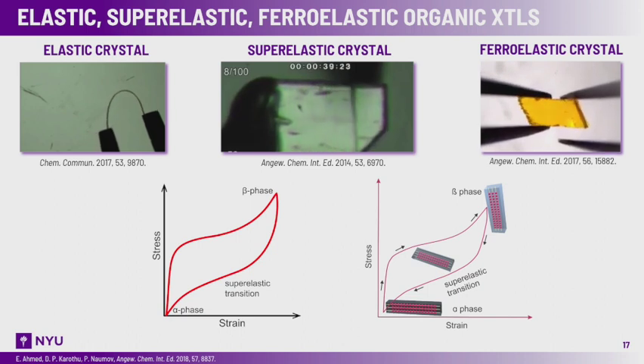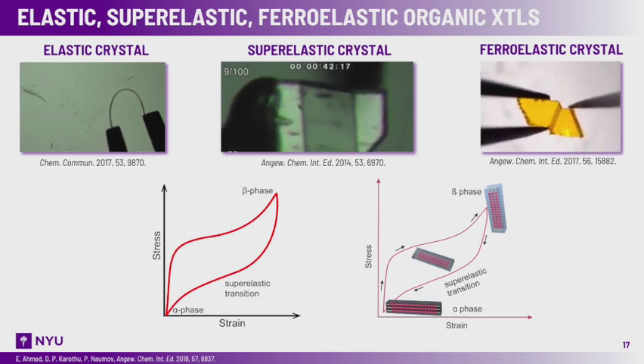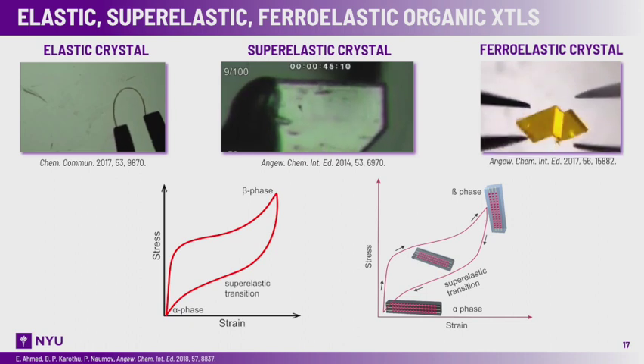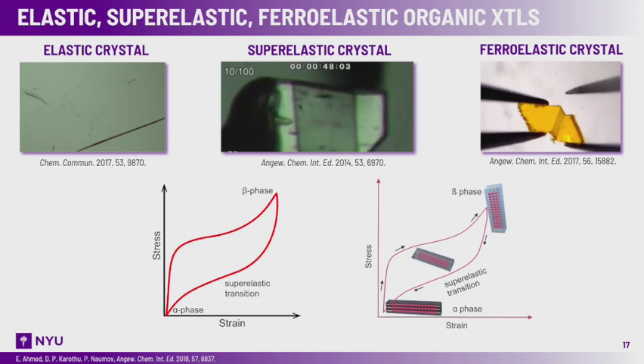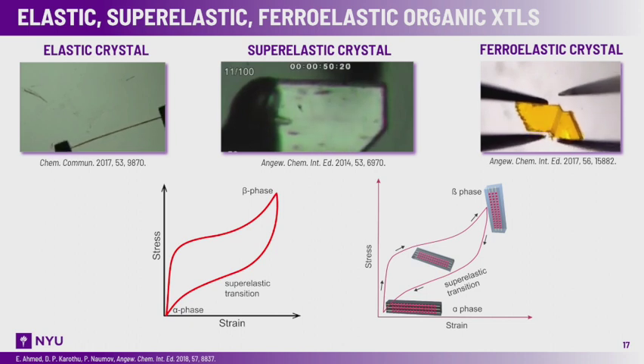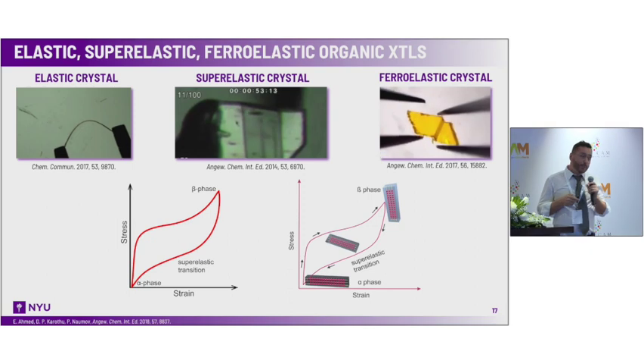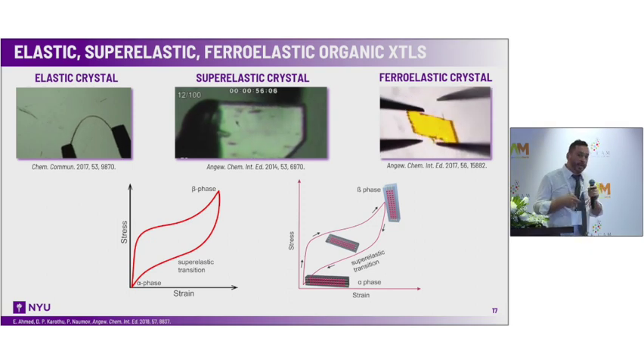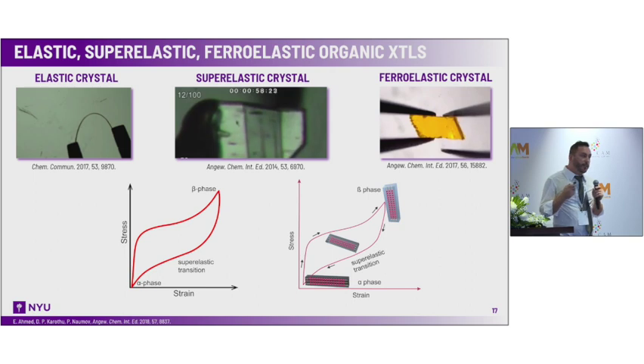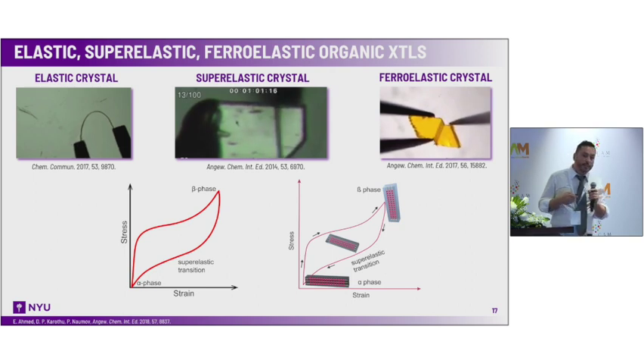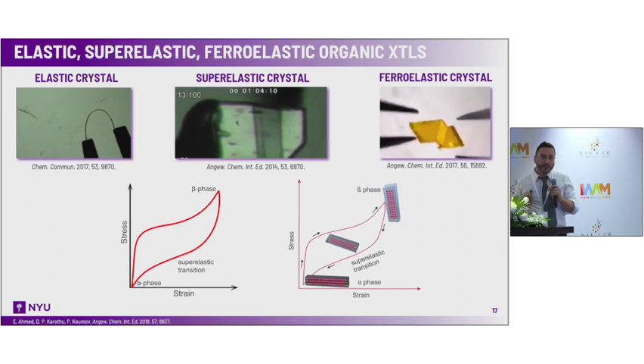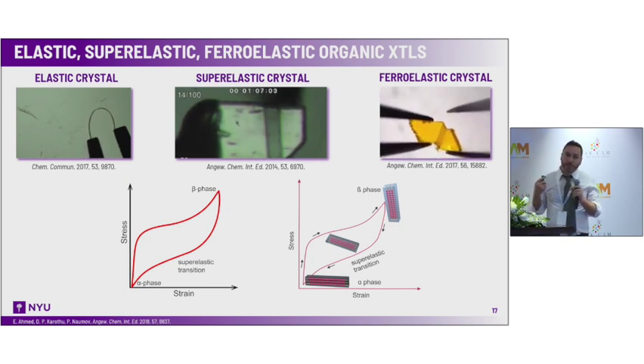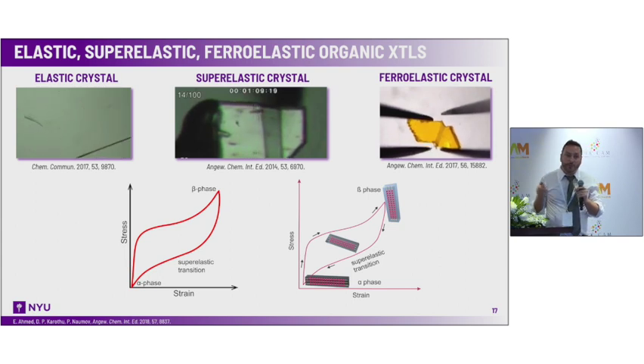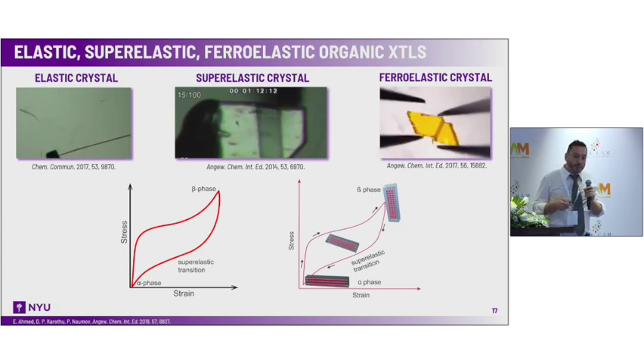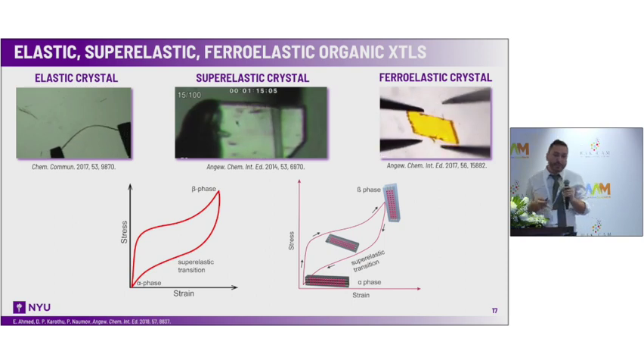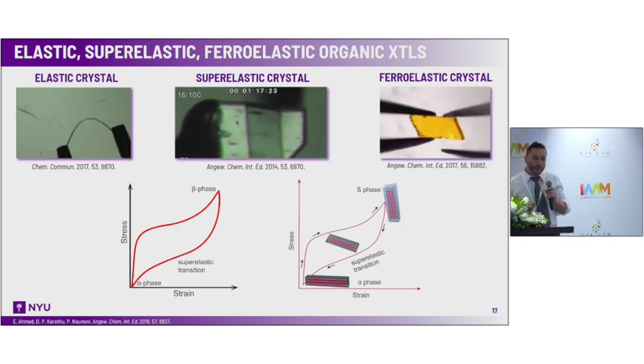If this is reversible, so the crystal reverts back to its original state, we have superelasticity. But if you have to apply force in the other direction to push it back, that's a ferroelastic crystal. These phenomena were recently observed for the first time in organic crystals. And not only do they resemble the same phenomena observed in metals, but I think there's a more fundamental difference, because in this case we're dealing with intermolecular interactions as opposed to metallic bonds. I think this is a really important area and provides a lot of room for additional